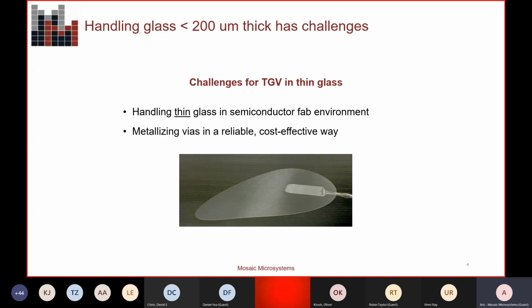So you can see from this picture, I think this is an 8-inch wafer, maybe 75 microns thick, but far too much gravity sag to process in a semiconductor environment, right? Not only would your sensors be going crazy, but you'd literally be running into things just because there's too much deflection in the glass.